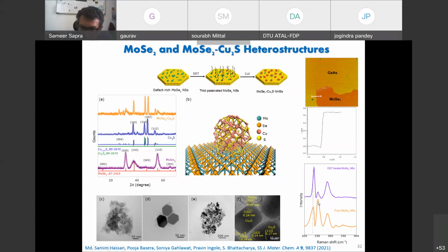And what you see over here is again the Raman spectrum, and this is your E2g and A1g peaks. But then in our cases, we also get this huge peak in between, which is attributed to the defect sites. And when you passivate these defects, this peak goes down. So you do know how much defects you have, and whether you've passivated them, you've gotten rid of those defects. So that can be addressed by using Raman spectroscopy.